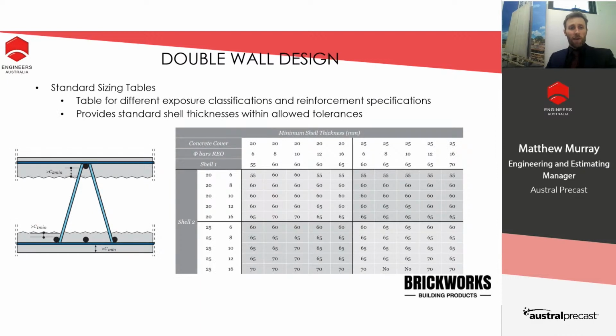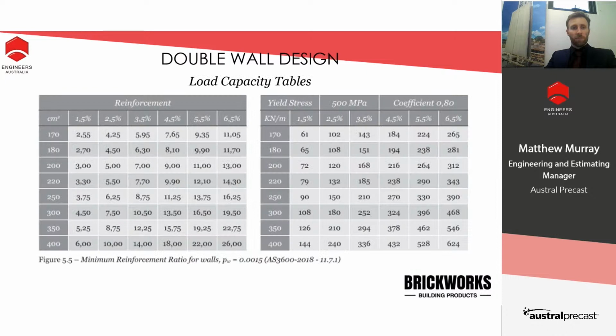So as part of our technical manual, we also have the standard sizings available. The key with double wall is the internal cover from the inside of the longitudinal bars of the girders and the core. It's the most critical part for the temporary state. So typically we need this C-min value that you can see here on the picture on the left to be at least a minimum of 15 millimeters, and the size of the girder and the overall thickness of the panel will be dictated by the overall size of the wall that's required, the cover, and typically the horizontal bars, as the girders sit on the horizontal bars of the panel. We also have load capacity tables available based upon the minimum reinforcement requirements and the different thickness of walls.